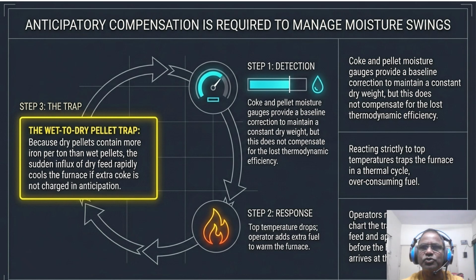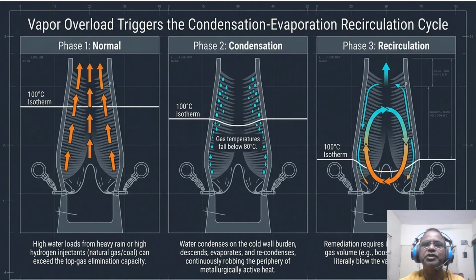not just the state. So if this moisture is not managed, it doesn't just pass through, it begins to recirculate in a destructive cycle. When we exceed our top gas elimination capacity, we trigger the condensation, evaporation, recirculation cycle. Narrating from left to right, phase 1 shows the normal 100 degrees centigrade isotherm. In phase 2, look at the wall region. Gas temperatures fall below 80 degrees centigrade, causing water to condense on the cold burden.